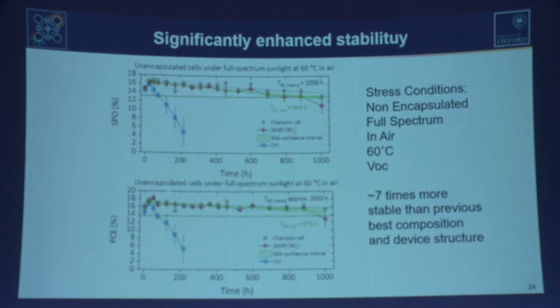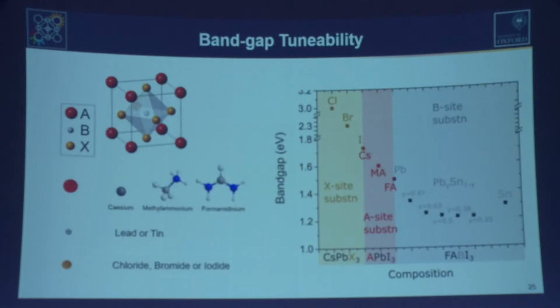One of the key challenges for perovskite solar cells is how do we make these materials fundamentally stable so they'll last for 25 years when deployed in the field. Because these are salts, crystallized salts, that's one of the reasons they crystallize so well at low temperature, but it means they can be sensitive to things like atmospheric moisture. They can be more sensitive to temperature than silicon. So we need to tune the material and work out what additives we need to add and how they influence the stability.